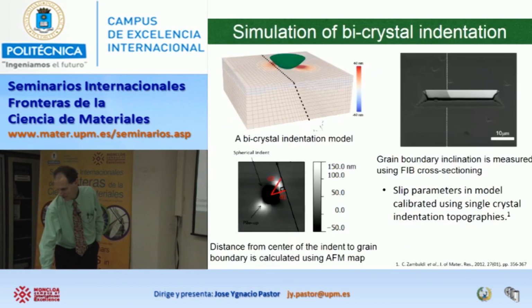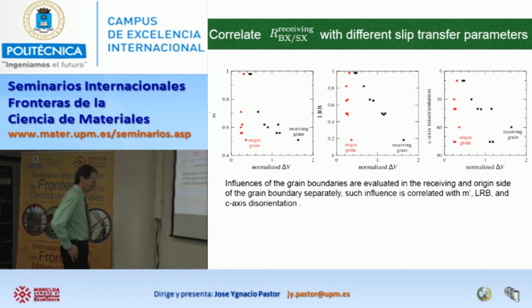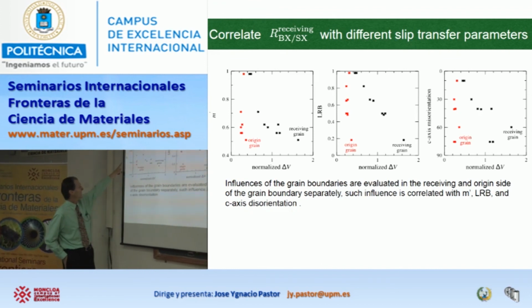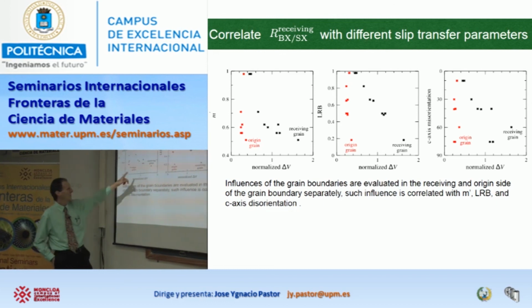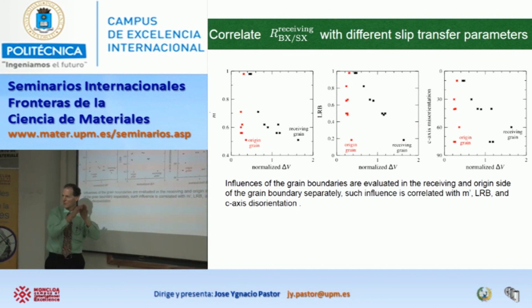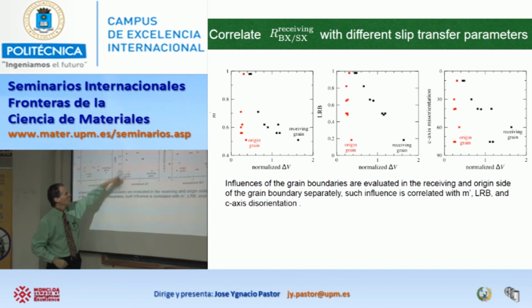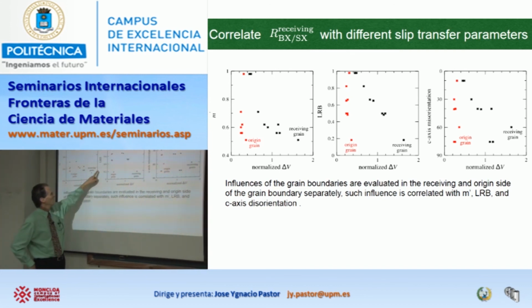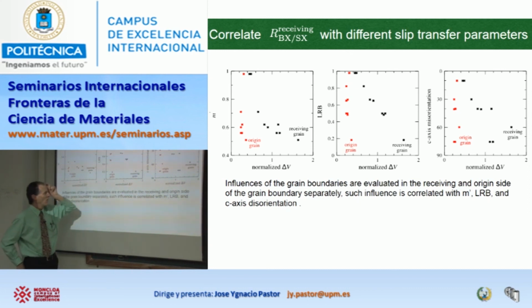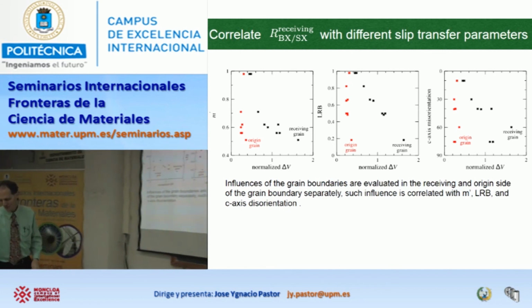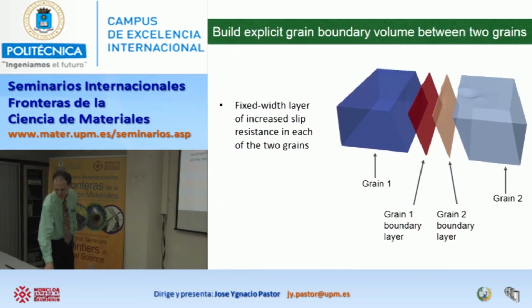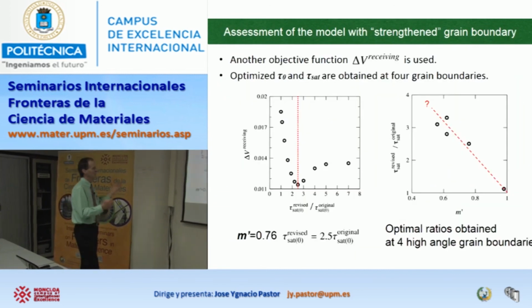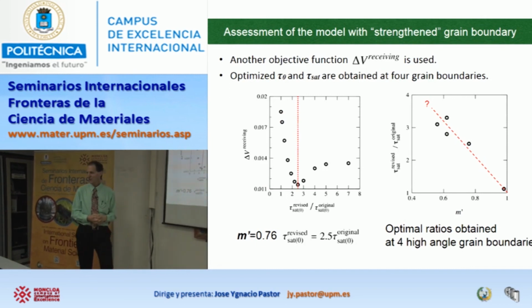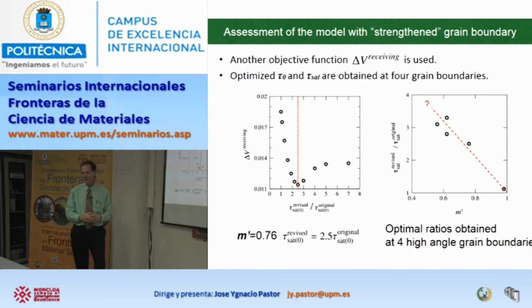And let me go back to this one. Also, we can compare this M prime parameter, which I mentioned to you before, along with another one, the one that involves the tilt in the grain boundary plane, where there's a mismatch of two slip planes. This seems to do a pretty good job, too, of making a relationship between a volume difference with respect to this parameter. Okay, anyways, that gives you the sense that we're beginning to be able to say that maybe we can simulate what's going on at a grain boundary and actually plug it into a model that can become predictive.